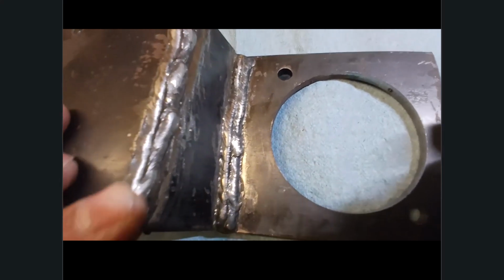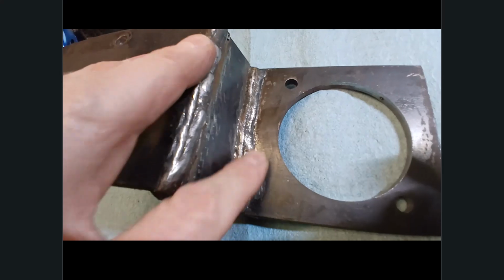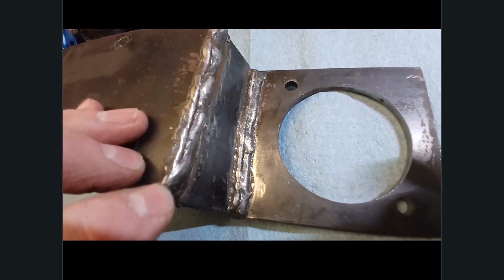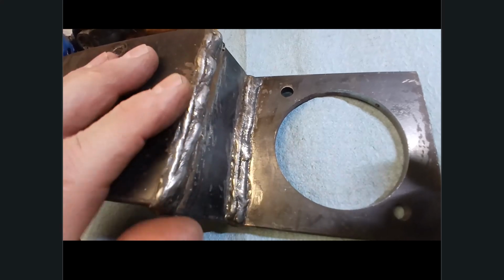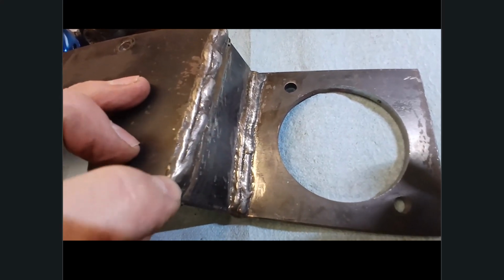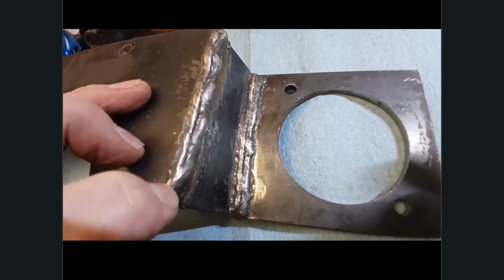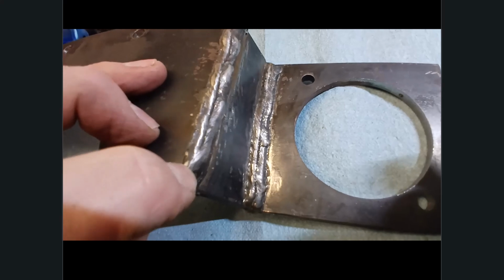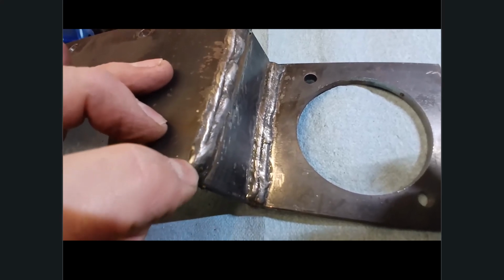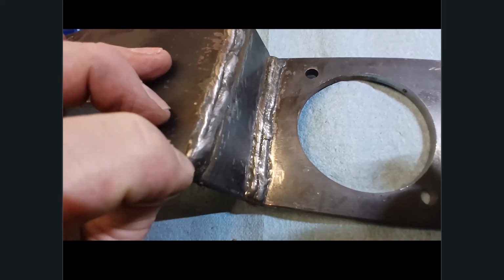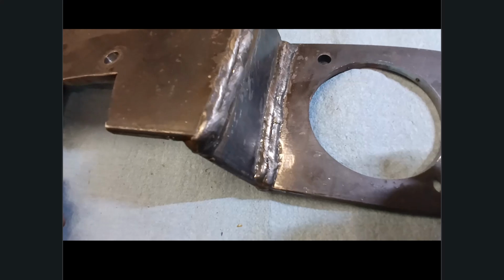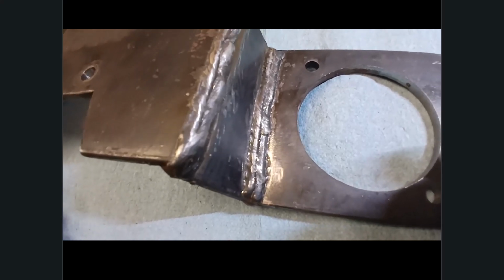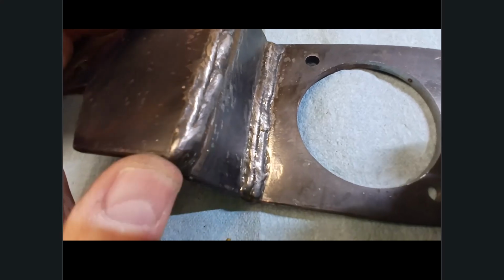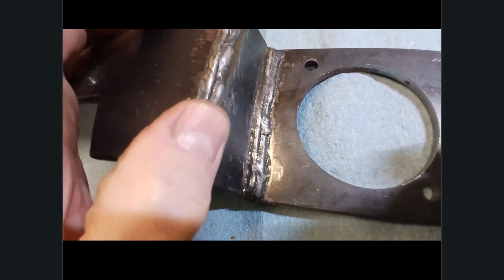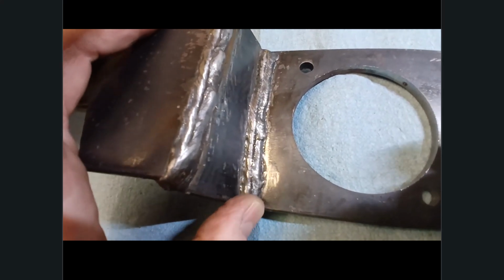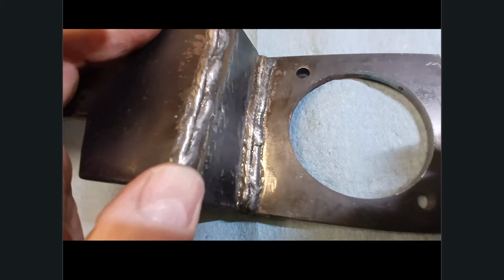So I was quite fortunate. I only had to grind down a couple spots on some starts and then reflash those over, and then they were repaired. The reason you do that whenever you see porosity is that you'll see some very small holes, half of a millimeter, very small, but it'll look a little bit like a spongy surface. You have to grind those off and then weld that and repair it. You don't want to leave those holes because they can form cracks and compromise the strength and durability of your welds. They're compromising to the structural strength of the welds that you're laying down, and therefore you have to hunt them out.